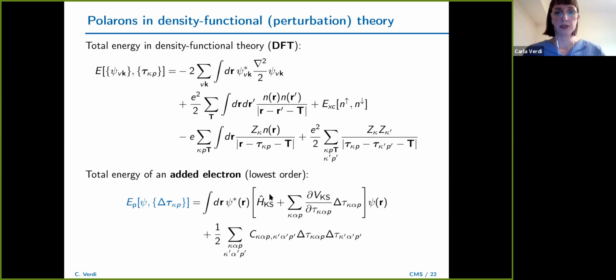And you see it includes the Kohn-Sham energy. This is the Kohn-Sham Hamiltonian of the ideal crystal. And this is the derivative of the Kohn-Sham potential with respect to phonon displacement. Delta tau is the phonon displacement. And of course, psi is the wave function of the added electron. And then this extra term here has C, which is the usual matrix of interatomic force constants. So this is basically the elastic energy of the lattice.